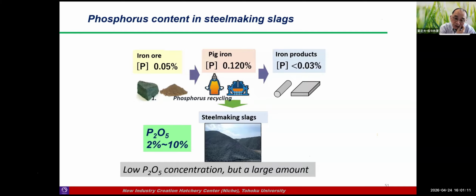The problem is that the P2O5 concentration in steelmaking slag is relatively low compared with phosphate ore or sewage sludge. But the amount is so large, so we should somehow manage to recover this. It's very challenging.